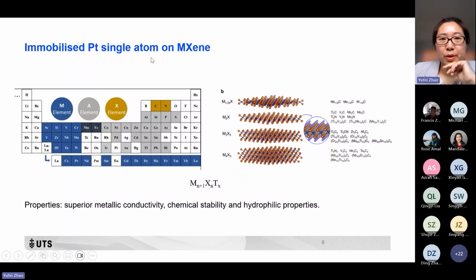The first substrate we have chosen is MXene. We know MXene is a two-dimensional material. It is a metal carbide, metal nitride, or metal carbonitride. MAX comes from the MAX phase. Normally for MXene, we need to etch the A element out to achieve the MXene phase. By changing the metal type and also the N here, we can achieve different kinds of MXene. So we have a lot of choice by using MXene as a substrate. There are also a lot of advantages of MXene. We can see it has superior metallic conductivity, chemical stability, and also hydrophilic properties.